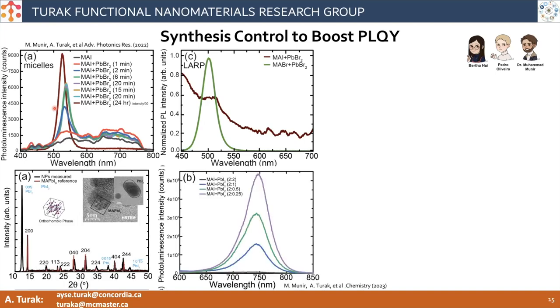Additionally, because we separated out the two different components, typically if you're adding these two precursors together in solution, because they react so spontaneously, it's hard sometimes to control the composition, if you want to get a mixture of two different halides, for example. By separating out these two steps, we were able to show that a lot of the extra lead iodide that we were adding was actually precipitating out of solution instead of forming nanoparticles. And by just eliminating that extra lead iodide, we can get almost an order of magnitude increase in the intensity of emission